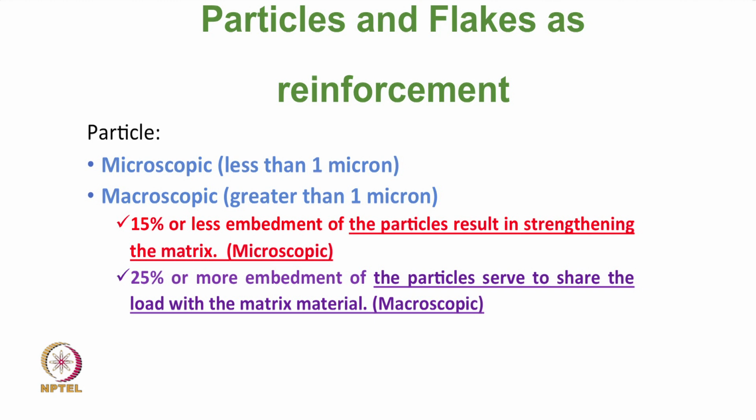In the microscopic size range, the proportion of these particles should be 15% or less, then the particle results in strengthening the matrix.